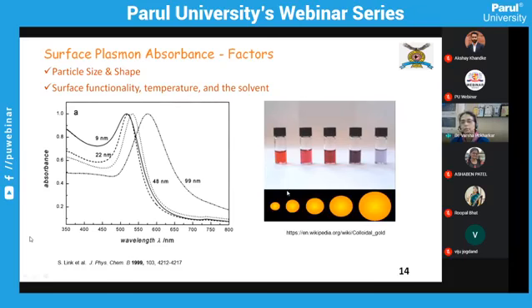So here is a picture. You can see that depending upon the size, the color of the gold sol is going to change. And this is obvious because as the size changes, the scattering intensity of the particle is going to change, and that is what will result in different colors of the gold sol. This is observed in the case of a particle which is spherical in shape, so you get only one lambda max or one surface plasmon band.